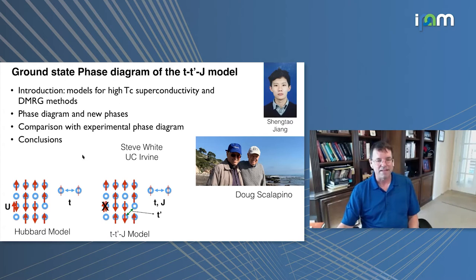We're talking about models of high TC. Here's a quick picture of some of the models. Basically, we think of electrons hopping around on a lattice. The electrons have spin. You could have in the Hubbard model a doubly occupied site, but that's penalized by an energy U. The hopping matrix element T hops things around. In the TJ model, we integrate out the doubly occupied sites, so those are no longer present in the Hilbert space. We just have the holes moving around. The removal of the doubly occupied states has introduced the parameter J, which causes antiferromagnetism, antiferromagnetic interaction between nearest neighbor sites.